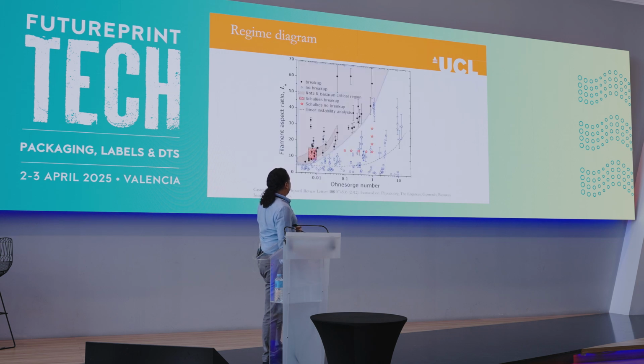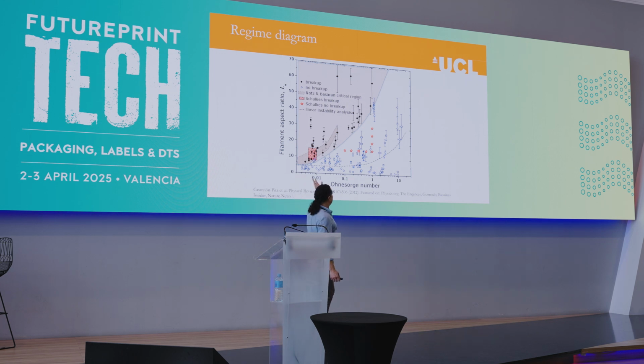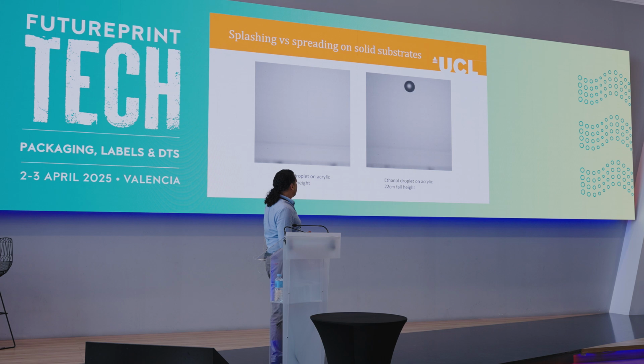Well, some other examples. And again, going back to a parametric scale, when you have dimensionless numbers in both axes, you can take your ink, you know the Ohnesorge number because you know the surface tension, the density, the viscosity, and the sizes. And then you can find at what point above this curve, everything breaks off into multiple droplets. Anything below coalesces into a single droplet. So this can be used for tuning your waveform or the liquid properties.